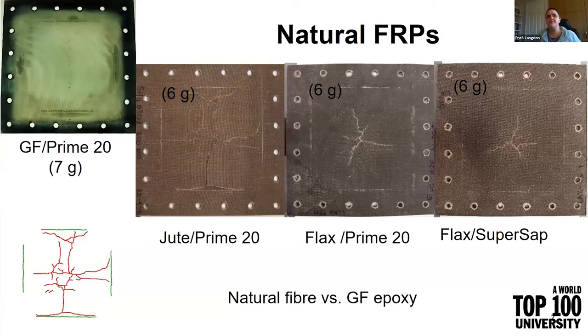So the flax and jute panels have ruptured at lower charge masses, even though they're so much thicker than the glass fiber. They're very brittle and they exhibit low strength compared to glass fiber. Fiber cracking is their dominant failure mode, whereas in glass fiber, delamination is a more extensive failure mechanism. And the reason why it's so important experimentally to determine the dominant failure mechanisms is because when we come to model these things, it's important to know where to put our computational effort. So with a natural fiber, such as the one shown on the screen, with these combinations of fiber and resin, you would be looking to model cracking more accurately. In glass fiber, you might be looking at delamination.